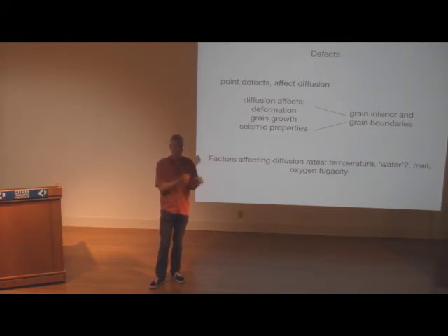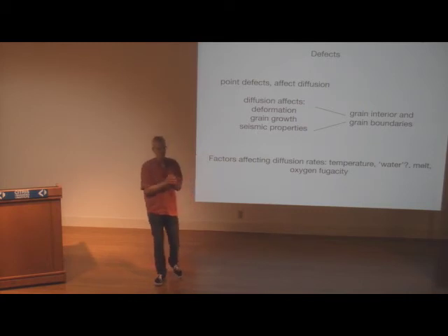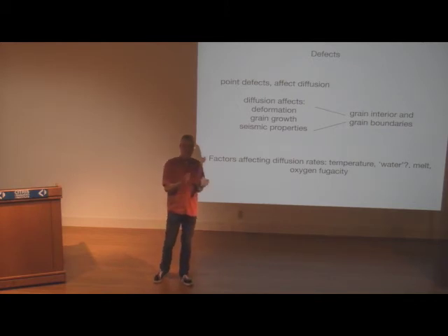It's all a little bit indirect because you, of course, never image that titanium atom in the crystal structure, but it's all consistent, the XAS and XANES data with the infrared data, with the ab initio modeling, that this is the change that you see. You take that titanium and move it around. That requires, of course, diffusion, and there's a time scale, so you don't do that instantaneously. So there are implications for how you do water incorporation experiments in olivine, for example.